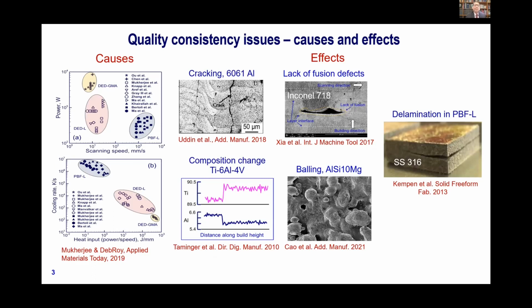But here is the difficulty. It's a relatively new process and it has its fair share of problems. And the cause of this problem can be traced back to one unique property of metallic materials. All metallic materials are notorious for their sensitivity to external impulses like thermal cycles and stress. And in additive manufacturing, we vary parameters very widely, like we are varying 100 times the power here. And on the x-axis, we have scanning speed that is varying 10,000 times. And as a result, we get very different cooling rates, temperature gradients, and other parameters that affect the microstructure and properties and serviceability of the products.